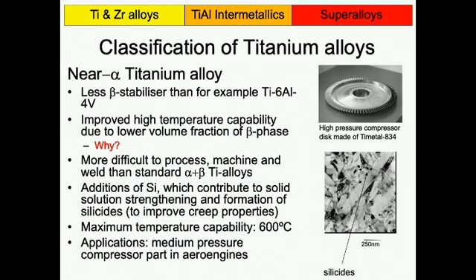It has improved high temperature capability due to a lower volume fraction of beta phase. The why we've already discussed earlier, right? You reduce the amount of phase which has high diffusion rates, and you improve the high temperature capability of that material, particularly creep. It is quite a difficult material to process in general. It's not easy to machine and weld.